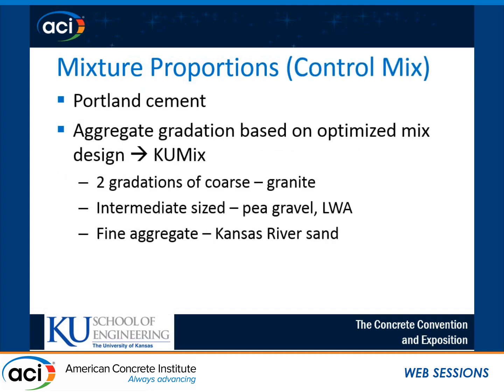Again, with our control mix, along with other ones, we use KU Mix, which is a mix design optimization program. And the aggregates we use with that are 2 gradations of granite, one with a 3/4 inch max size aggregate down to 1/2 inch, and then the other gradation is 3/8 down to number 8. We also use an intermediate size aggregate in the form of pea gravel. And for mixtures that we want to incorporate internal curing into, we use a pre-wetted pea gravel size lightweight aggregate and Kansas River sand for our fine aggregate.